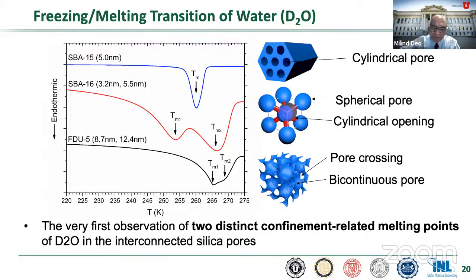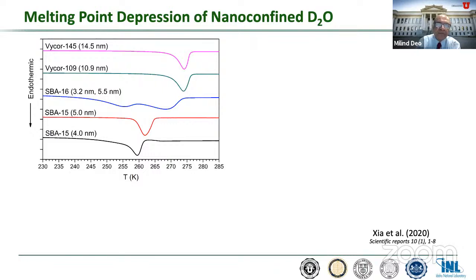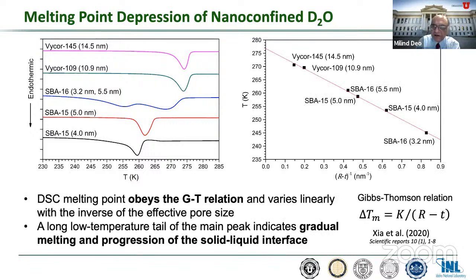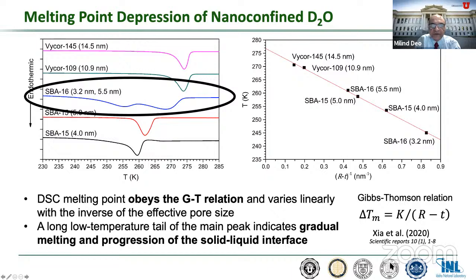This paper was also published in Scientific Reports, I think, in 2019 or so. And then we were able to take that data, the suppression data, and put it on a Gibbs-Thomson relationship to show that it actually does fit the freezing point suppression under nano confinement that, based on the pore size, the Gibbs-Thomson relationship predicts. We were quite happy to see that we are able to do this. So this is one part of the story. This is almost complete, I guess, in some sense, and the paper is in Scientific Reports.